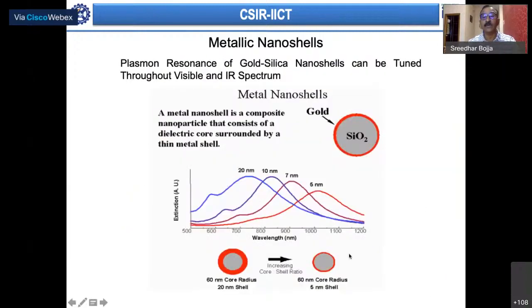This is the same thing: depending on the thickness of the shell, you can see a shift in the UV surface plasmon resonance peak, which gives us an idea about the thickness of the shell material. In this case, it was silica coated with gold. If it is about 5 nanometers, it corresponds to about 1050 nanometers wavelength.